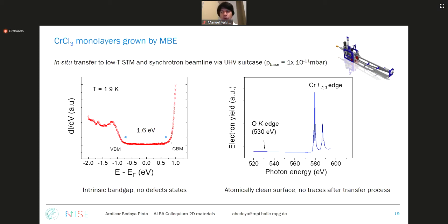There has been no theory regarding that, as far as I know, if any conditions will induce the charge transfer. What we know is that from the MBE growth, the van der Waals gap is really preserved, because from exfoliation techniques, sometimes you can apply more or less pressure, and the van der Waals gap can be more tuned, probably a little different. But in MBE growth, you have a peculiar growth mode that allows you to have this decoupling. So that's my answer to your question. Thank you.